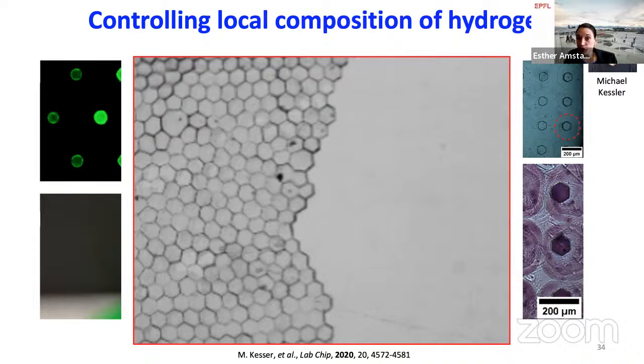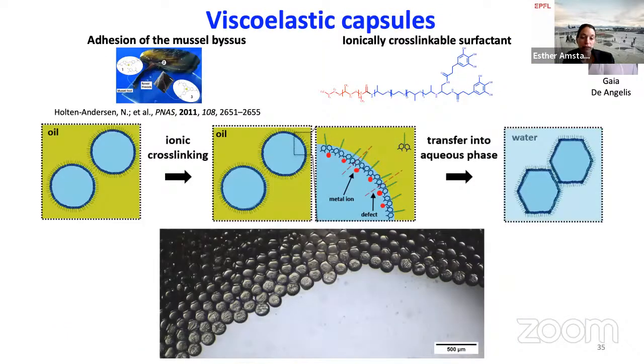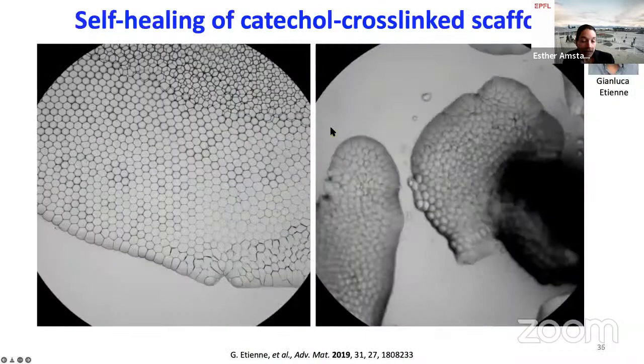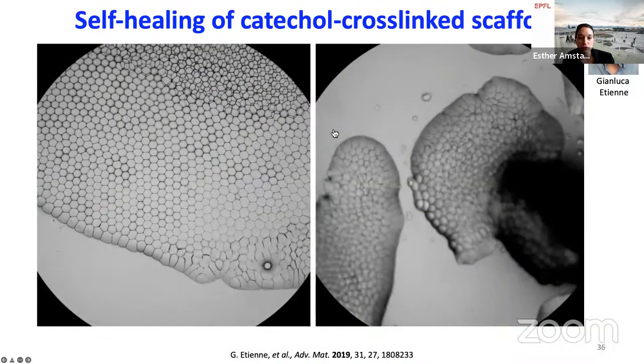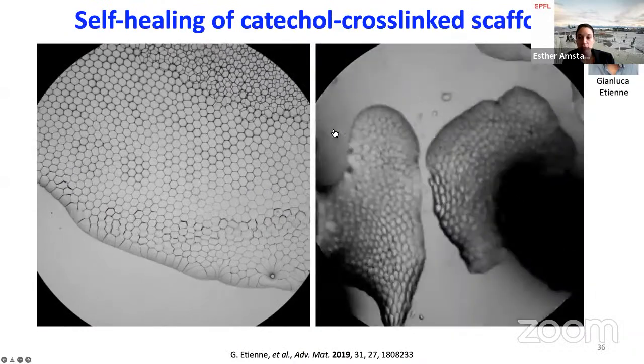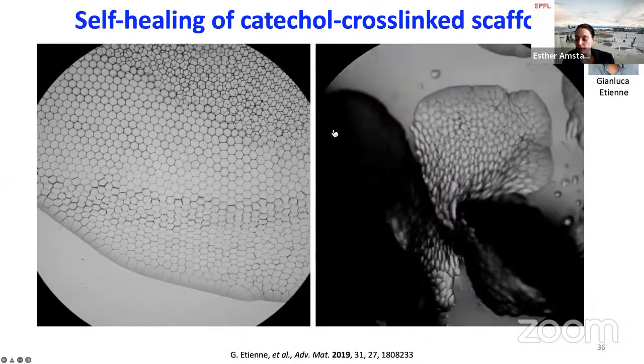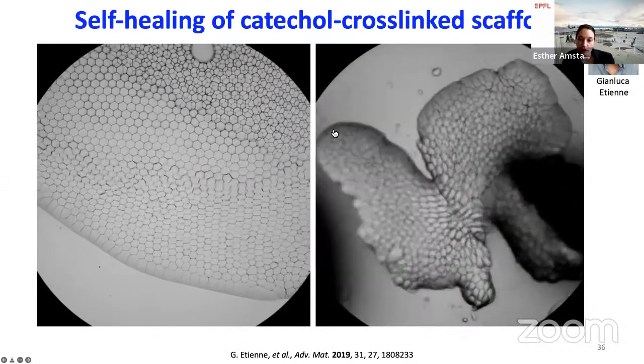Now, what does nature do to increase the toughness of this kind of material? It introduces reversible bonds that can dissipate energy. And if you think back on where I stopped with the capsules, with the viscoelastic capsules, we thought, well, we could use them as glue to increase the toughness of these kind of materials, right? So we could basically use our interfaces here as glues. And that is what we did. We did it first in 2D. We showed that you get self-healing properties of these kind of films in 2D. And then, of course, you can do the same thing in 3D.